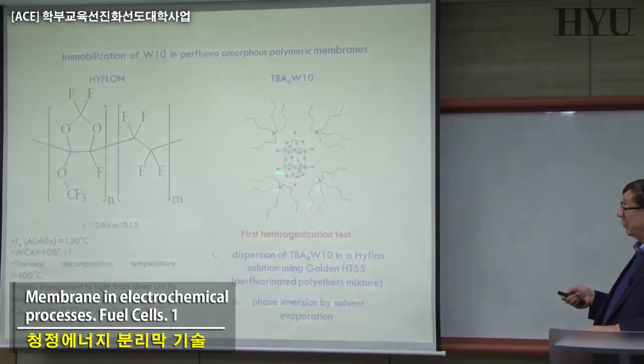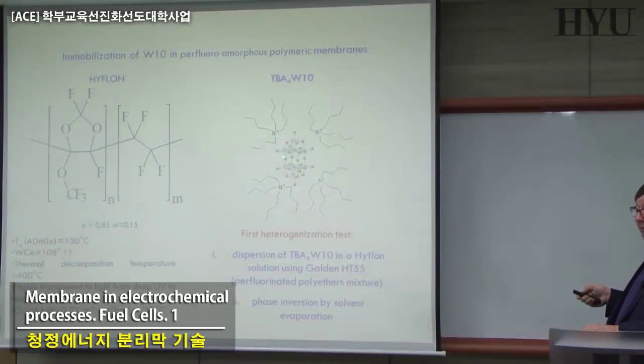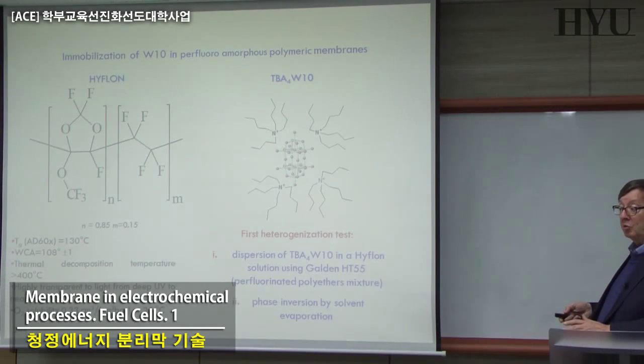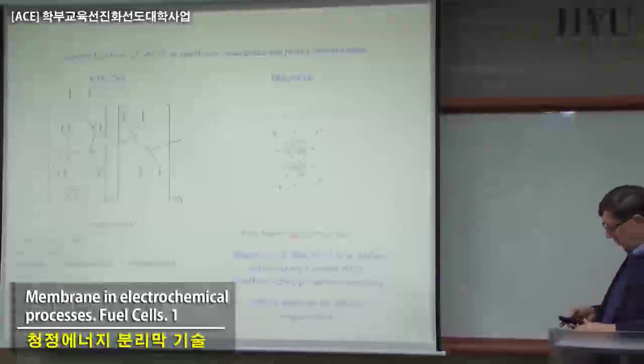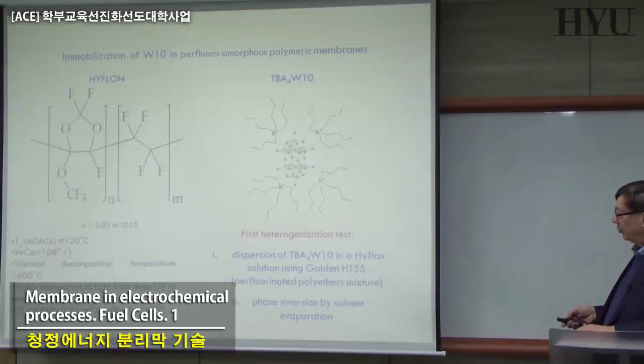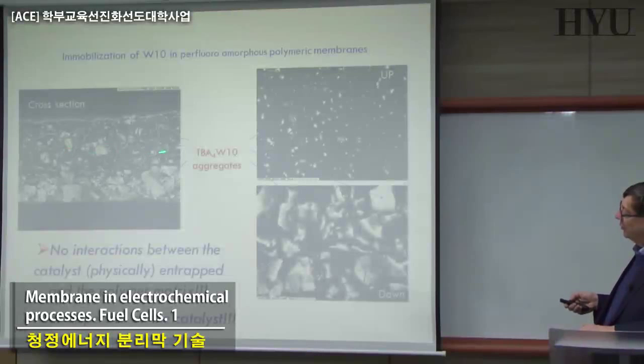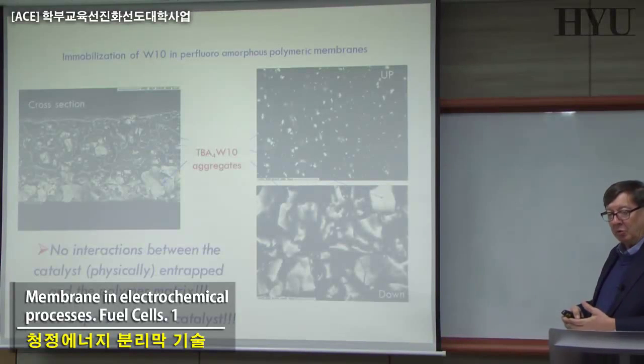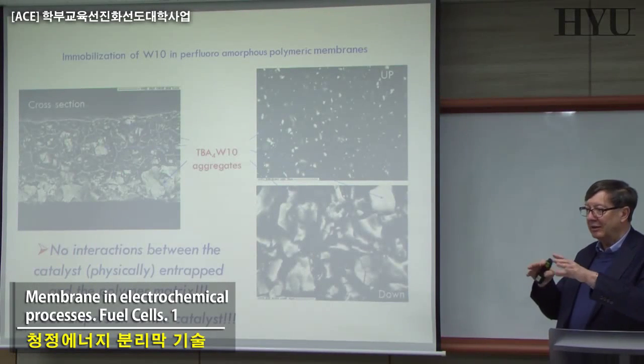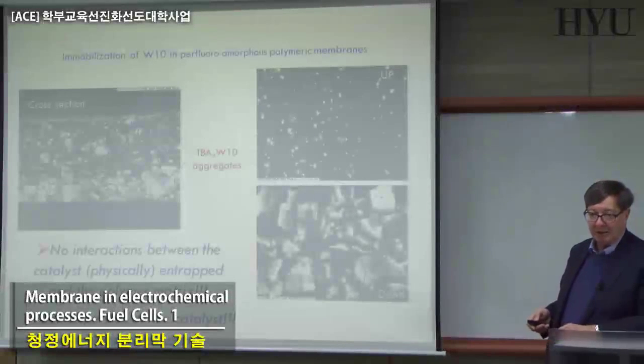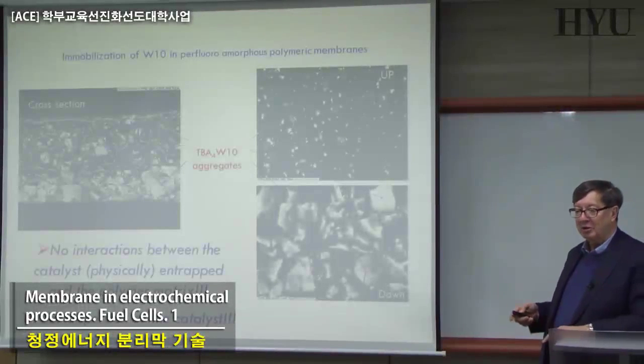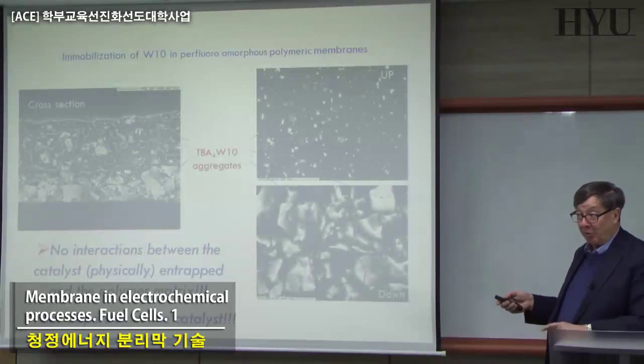And now, how to do it? You can take your catalyst, the same W10 that we have been discussing before in one of its forms, and try to disperse it in here, and try to have a homogeneous distribution, the one that we are trying to have. Otherwise, the catalyst does not work in an appropriate way. If you do this, the results are not interesting at all. This is the kind of structure you have at the end. There is basically no wettability between the catalyst, this W10, and the polymer that you want to utilize in this case. So no homogeneous dispersion as we obtained before with other polymers.